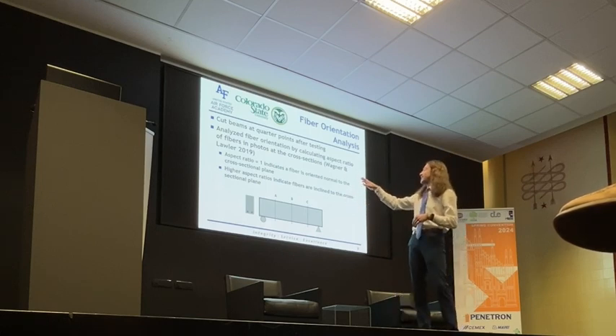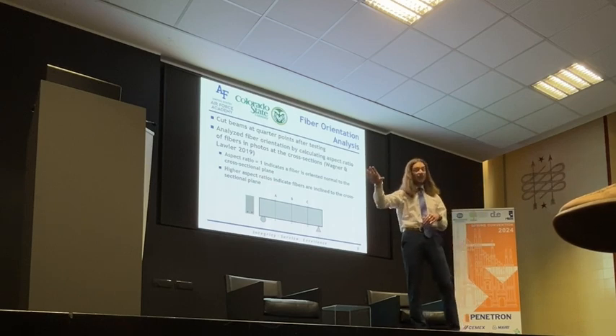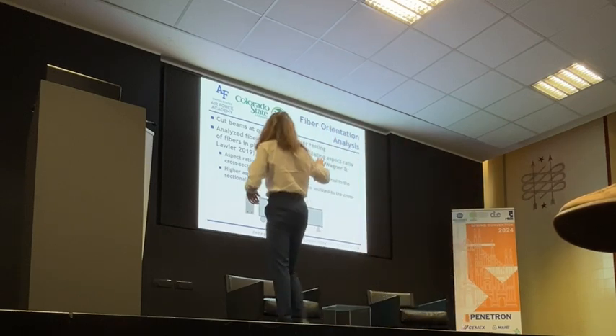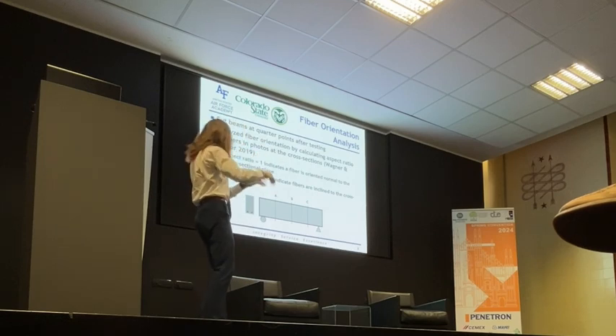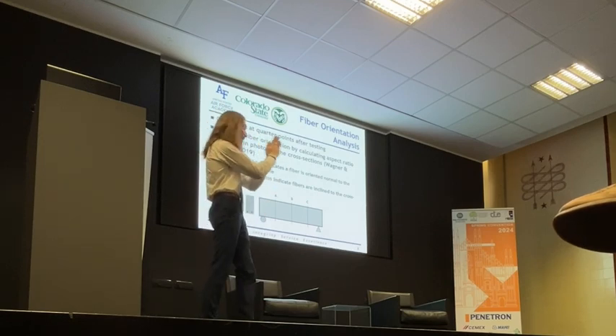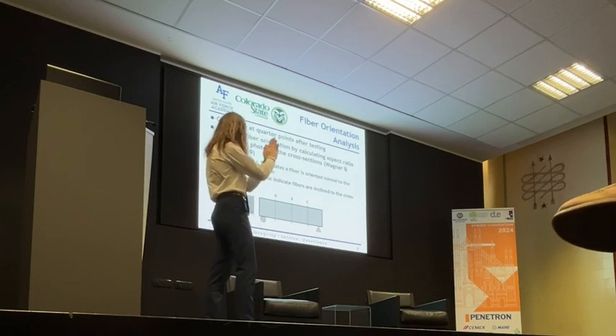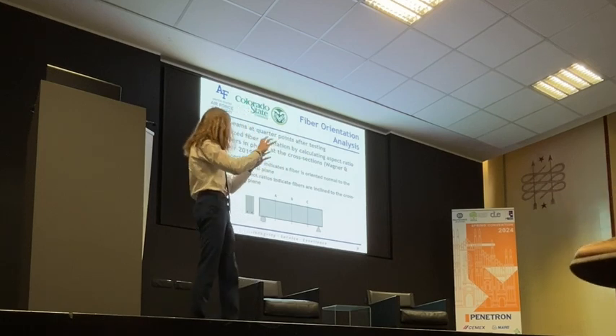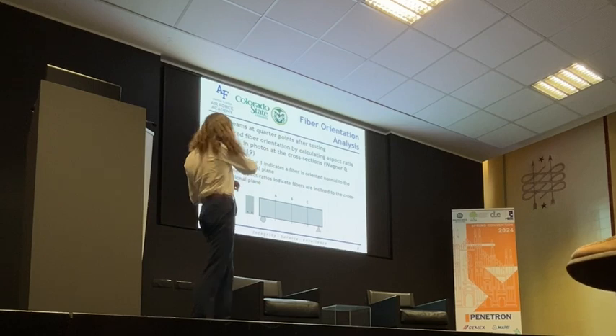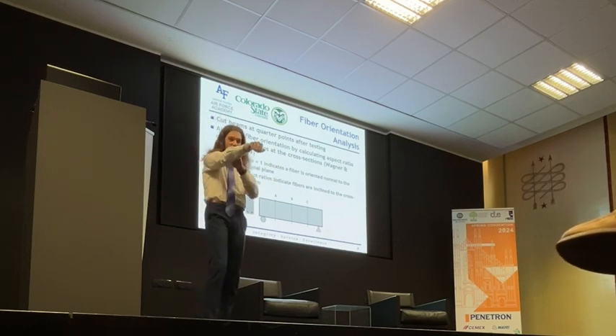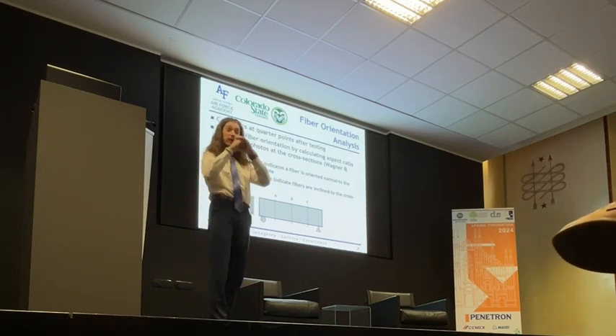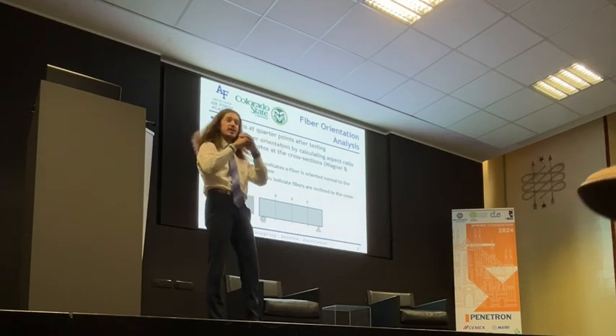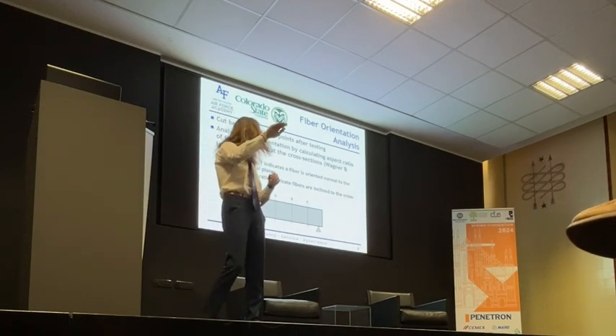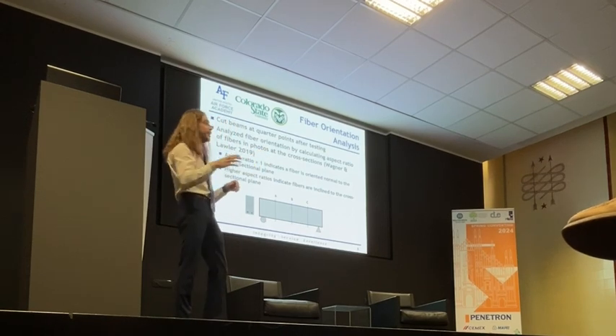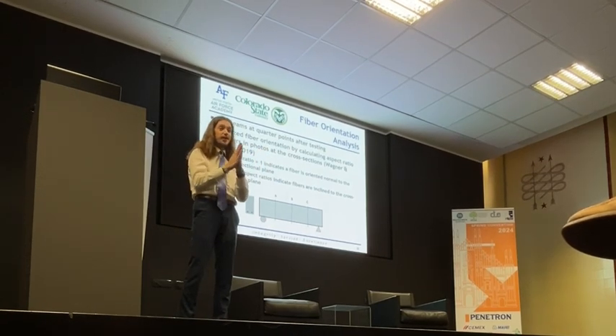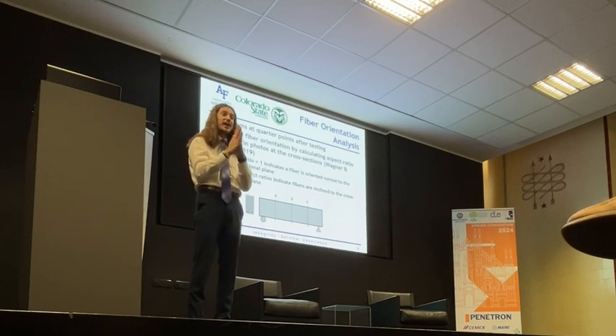So we have this idea of aspect ratio that was previously developed. And really what that is, if you imagine the screen is that smaller plane, that transverse plane, how are the steel fibers oriented? They're going to make an ellipse or a circle with that cross section. So if you think about it, you've got the steel fibers sticking out like this. If it's a perfect circle, it means that that fiber is completely perpendicular to that plane. And aspect ratio is the major axis of that ellipse divided by the minor axis.